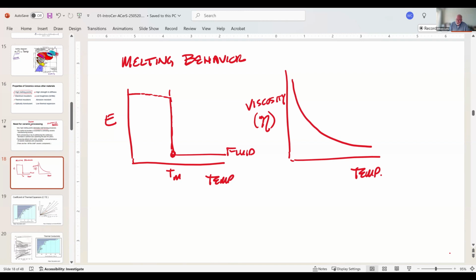So as I go up in temperature, my viscosity changes, but it isn't this abrupt change. If I were to look at a metal, the problem is I can't really represent it as a viscosity, but you might imagine that it comes across like this, and then it hits T sub m, which we're going to define to be out here for sake of argument. That T sub m in a glass is dictated by a specific viscosity, which is typically about 10 to the 1.5. But my metal would come across with a very, very high viscosity and then suddenly drop to a low viscosity at that point. This is a log scale, meaning that I might have 10 to the 20 here, and then 10 to the 10, 10 to the 5, etc. It's going to be a huge change in viscosity with temperature, but it's still very viscous.